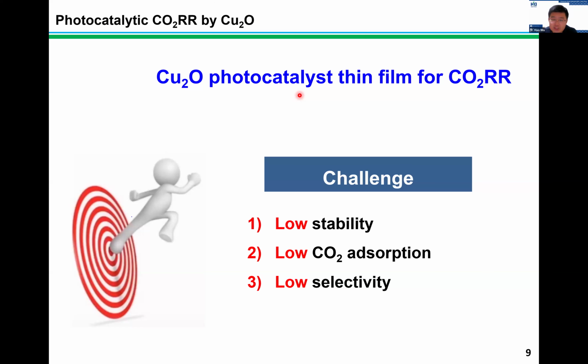Upon the light excitation, the generated electrons and holes can either reduce cuprous oxide into copper or oxidize cuprous oxide into copper oxide. In this situation, we will lose its visible light absorption ability, so lose its photoactivity. And meanwhile, as a bulk semiconducting oxide, cuprous oxide itself usually cannot provide abundant active sites for carbon dioxide adsorption and reaction.